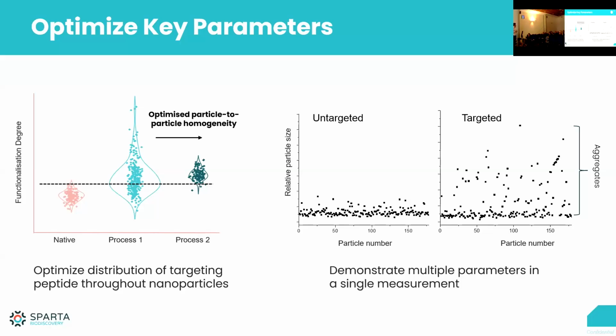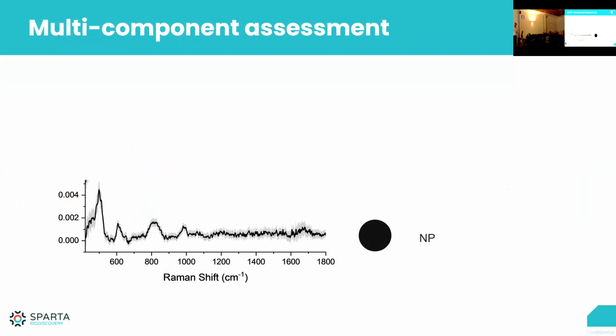Or maybe it's aggregates from your targeting ligand. If you're putting an antibody on the surface in the wrong buffer conditions, it could easily cause aggregation of the protein, and you have free protein aggregates in the solution. If you put this on a DLS, it will tell you that it's aggregates. It won't tell you what these aggregates are. Again, this gives just a lot of insights for optimization.